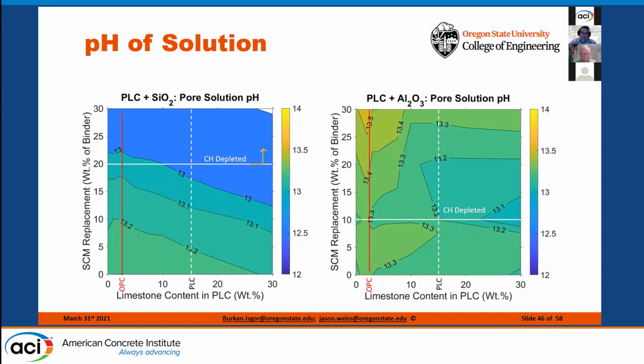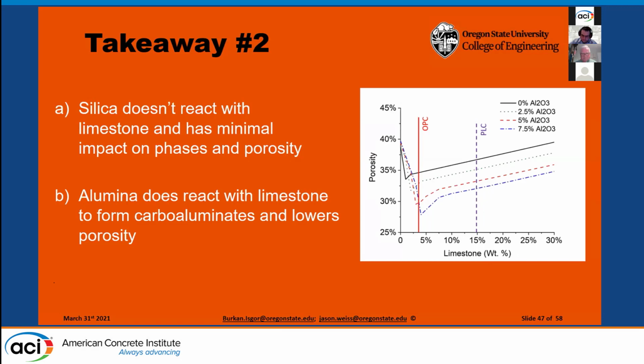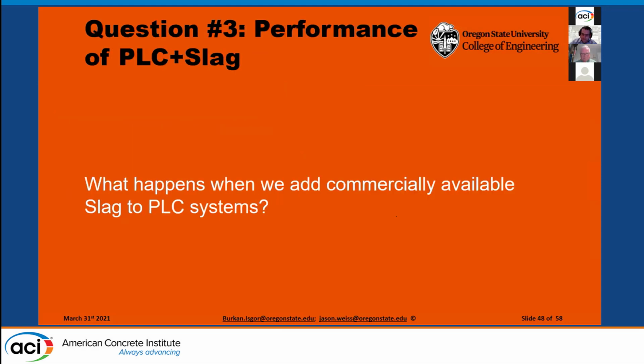But what you notice here is the pH changes slightly, but it doesn't increase in any way when you start to use your PLC. In fact, there's a slight decrease in the system. So again, the real takeaway: silica doesn't have a huge impact with the limestone and really has a minimal impact on the phases and porosity. Alumina, however, does have a major potential to react and actually creates a substantially lower porosity in the overall system.